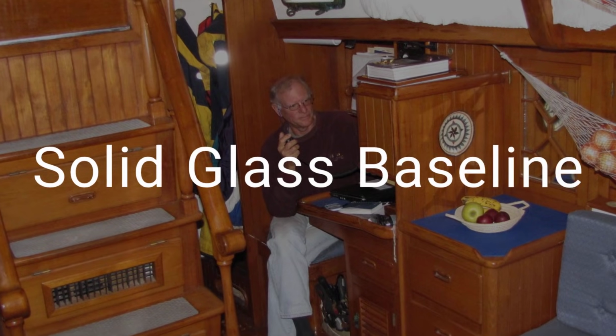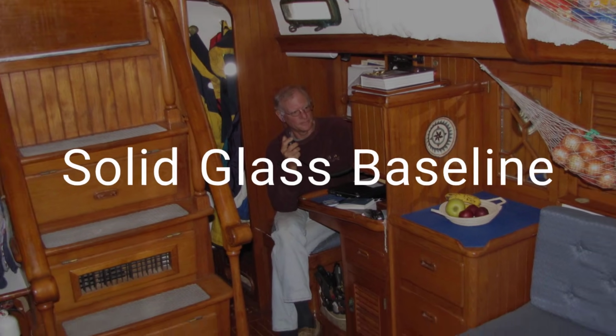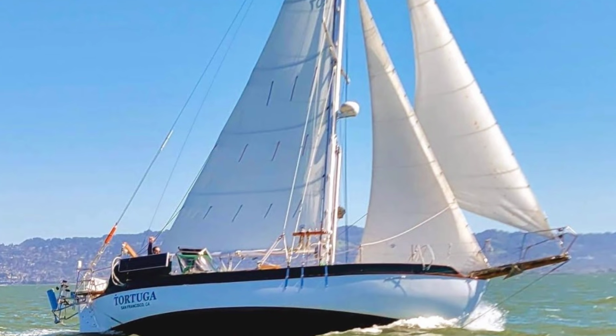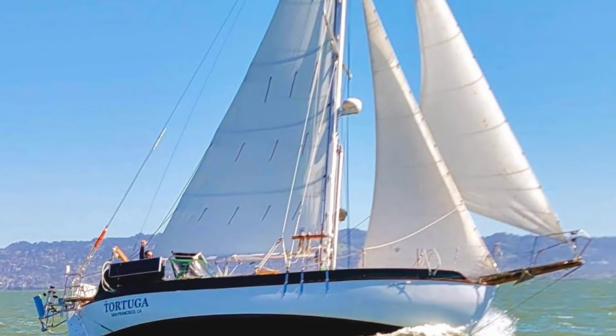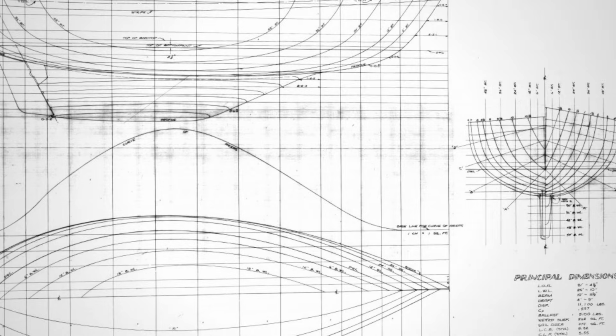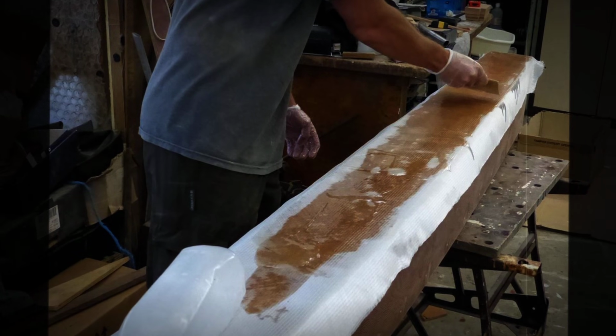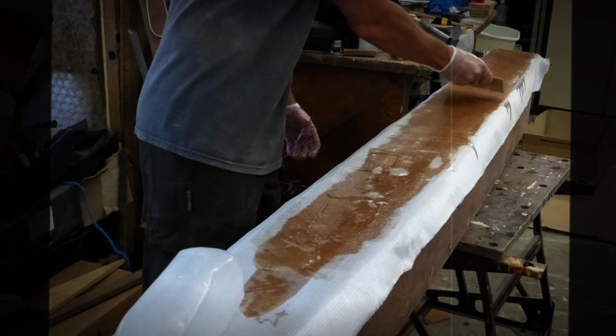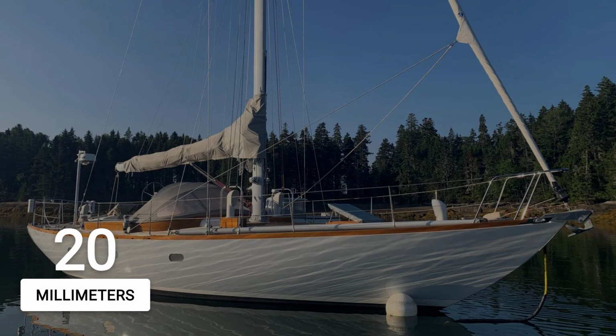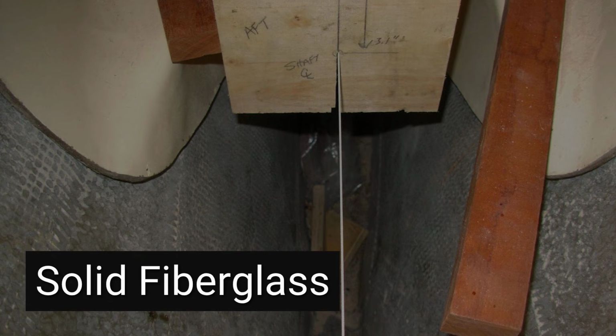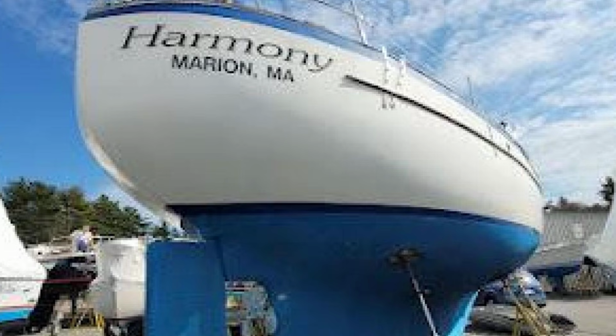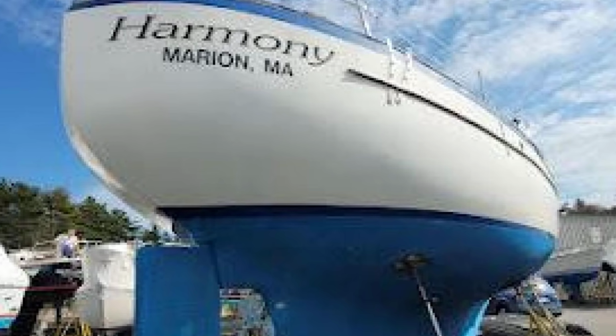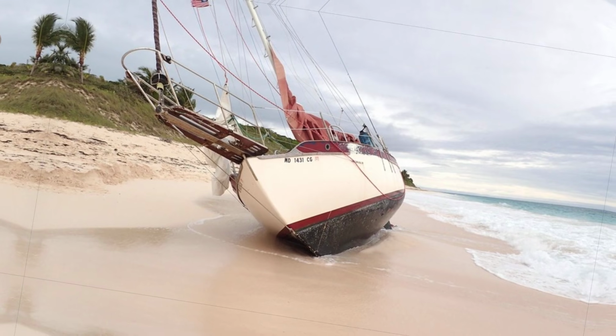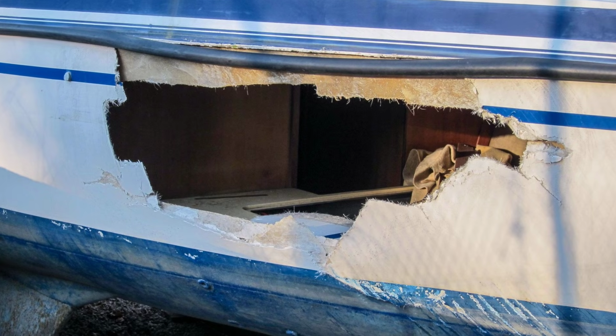Step into the hull of a Westsail 32 and you're surrounded by a different philosophy, one that treats a sailboat not as a disposable product, but as a permanent ocean-going structure. The hull here is solid polyester fiberglass laid up by hand in thick, overlapping layers. Midships, the laminate is a full 20 millimeters, nearly an inch of solid glass, no core, no foam, nothing to rot or delaminate. At the keel, the thickness increases again, a silent promise that this boat was built to shrug off groundings that would total a modern yacht before the insurance adjuster even arrives.